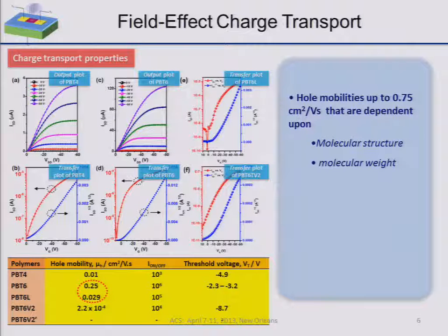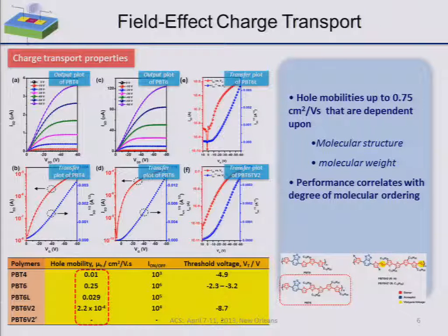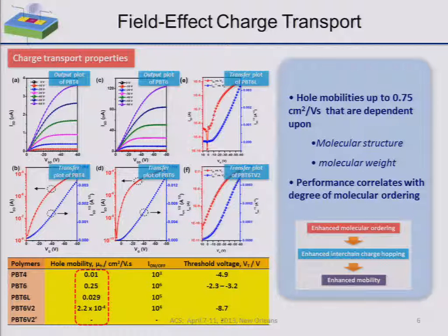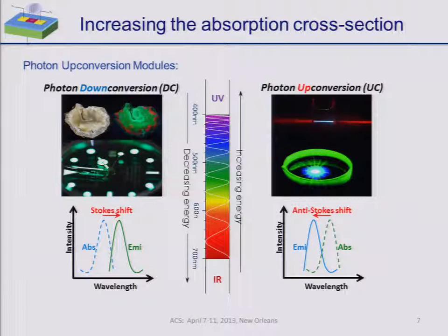We can characterize those devices, and we can see hole mobilities that are as high as about 0.75 centimeters squared per volt second. They're dependent upon the actual molecular structure. They're dependent upon the molecular weight of the system. And importantly, they're also dependent on the processing that we do on the polymer so that we can actually manipulate the charge transport characteristics. The performance also correlates with the molecular ordering of the system, and that we've been able to confirm using X-ray diffraction studies, where enhanced molecular ordering does lead to enhanced interchain charge hopping, getting enhanced mobility. All right, so that's one aspect where manipulating molecular structure, manipulating processing, we may be able to improve performance.